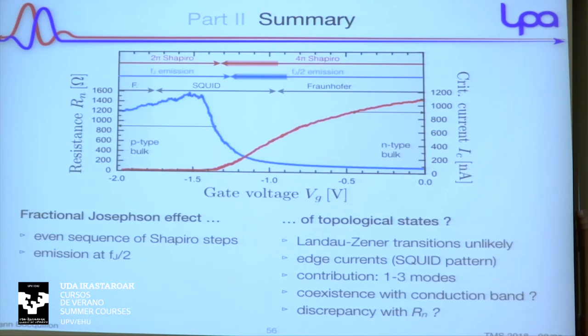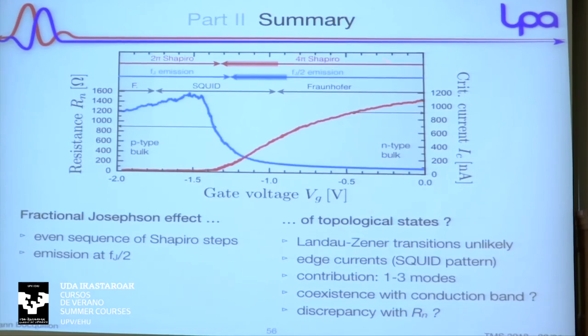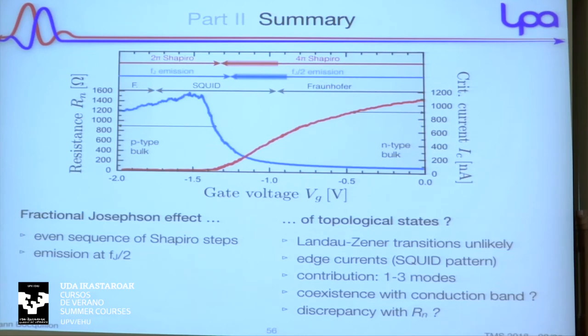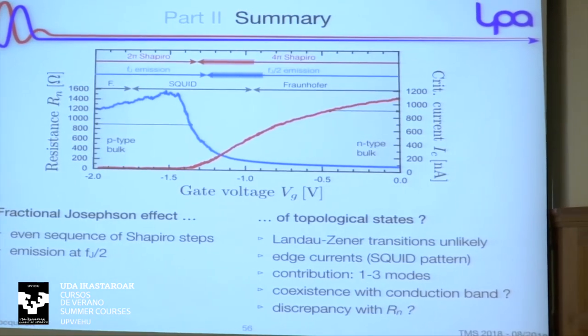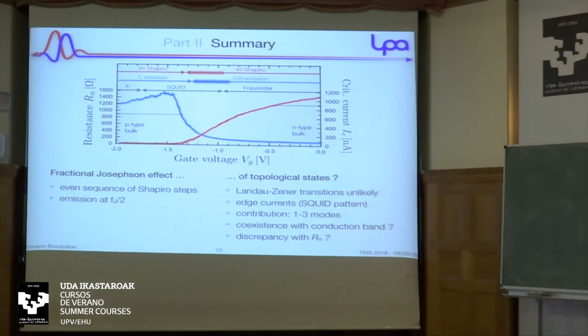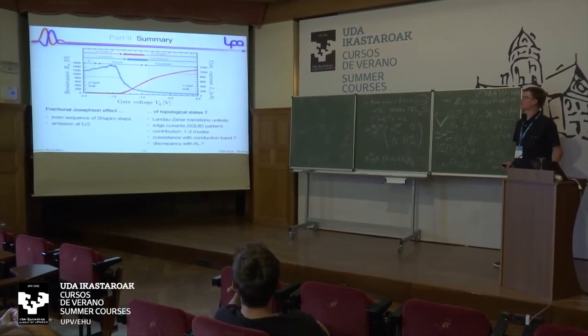In particular, if you look at the band structure, you can see that because of the flatness of the valence band, the quantum spin Hall edge states are rapidly killed in the valence band, but can survive next to the conduction band for up to very high energy, and they can coexist in principle according to band structure calculations. This is one possible explanation. But again, this calls for more experiments that will actually confirm this topological origin of this 4-pi periodicity.